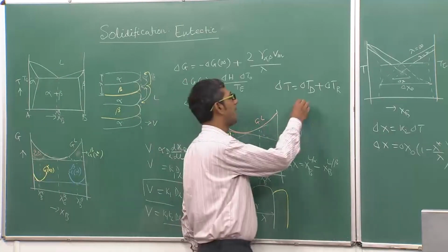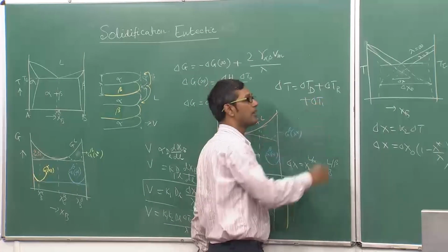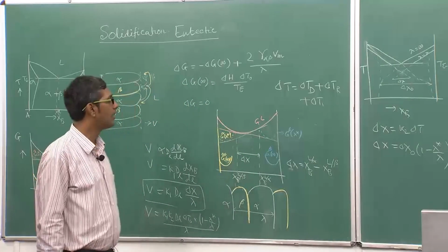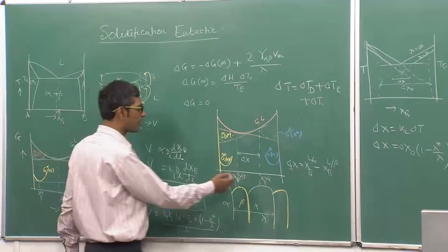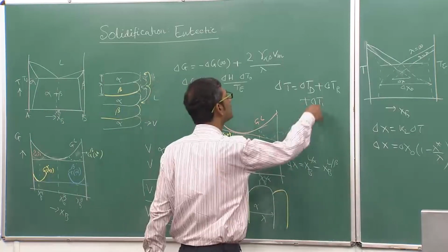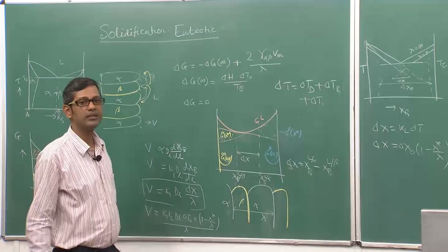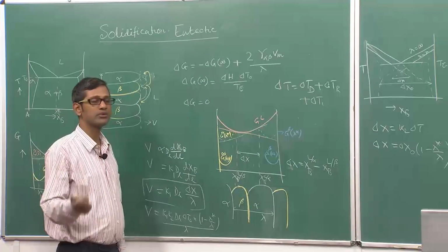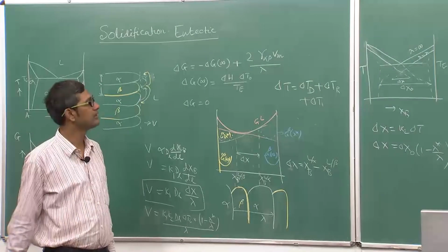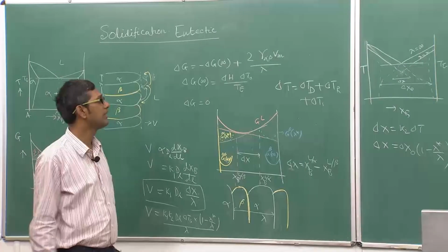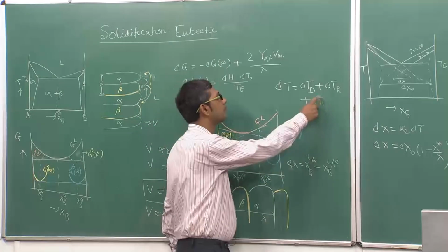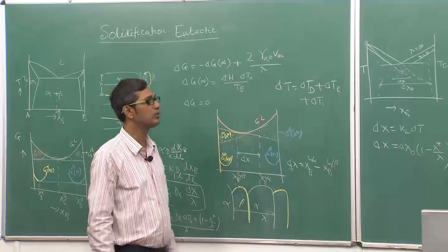And sometimes people also add another part, known as interfacial undercooling. This value corresponds to the undercooling required for the atomic jump from the liquid to the solid. Normally it is very low when the interface is rough, so the atoms can easily jump across. But when the interface is faceted, like in an aluminum-silicon type eutectic, this value is very high, and one must add this component to the total undercooling equation.